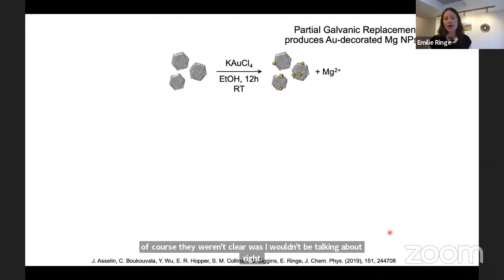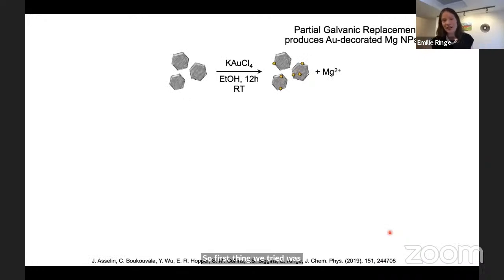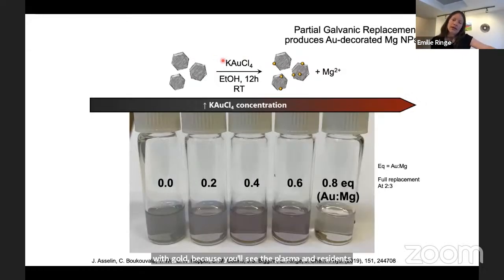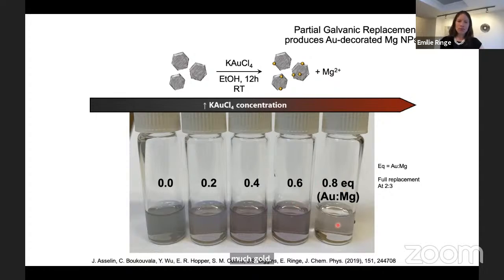So first thing we tried, well, is the easy way out really, try with gold, because you'll see the plasmon resonance of gold appear if anything happens, and it does work, okay? So as we increase the amount of gold, we are seeing more and more gold particles, more and more of that sort of purple-red color, and eventually if we put too much gold, everything crashes in solution.